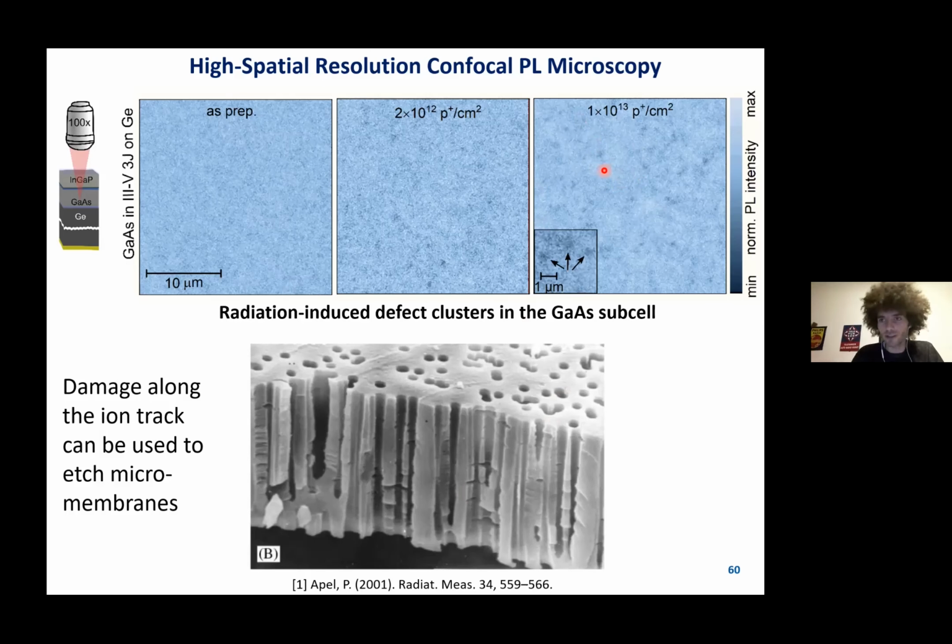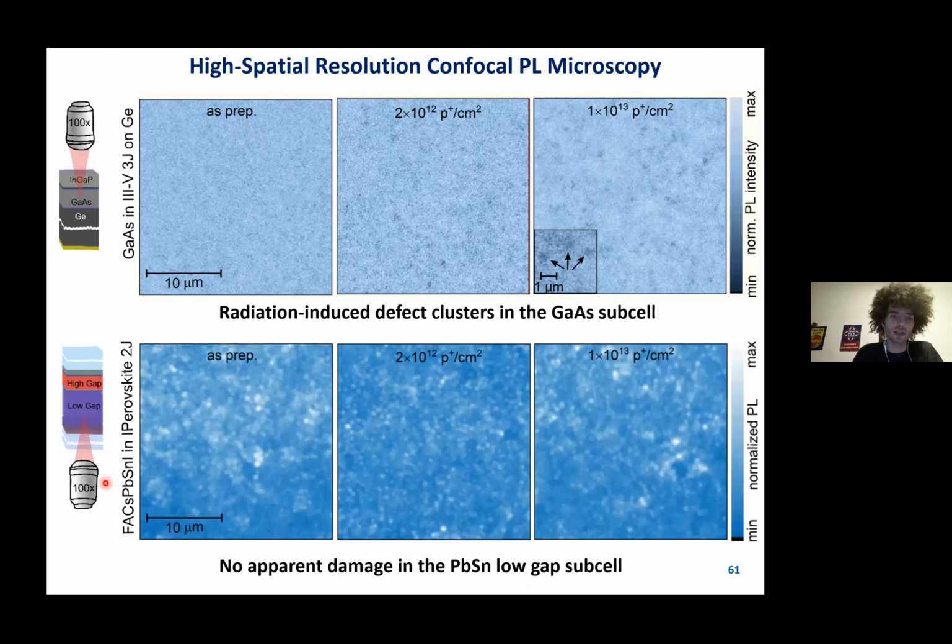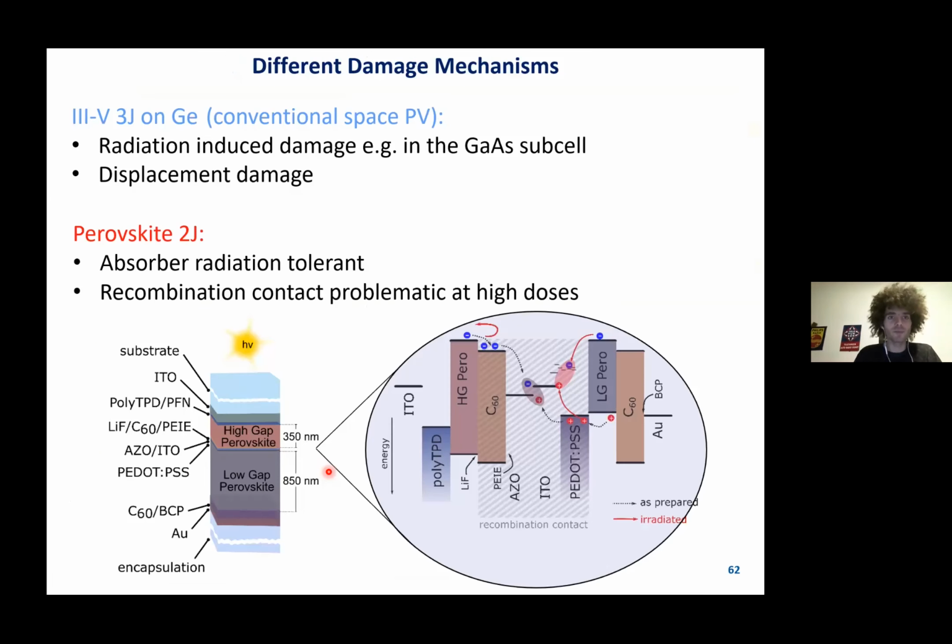All right, so we of course did the same for the perovskite. And now I'm jumping directly to the low gap perovskite because that one was damaged the most. However, we don't see the appearance of any dark spots, but of course perovskite is not epitaxially grown and is a polycrystalline material. So it's also hard to see. But overall, we think that damage in III-V semiconductors is quite different from damage in perovskites. So in the gallium arsenide subcell, we see these defect clusters because of displacement damage. But in the perovskite,